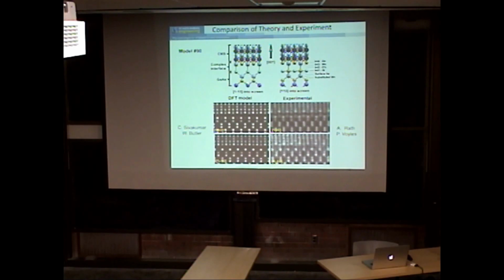Okay, so here now is a model, and you can see here they're trying to simulate this experiment. This is a theoretical image. They're close. I would say they're not perfectly matched. This was model number 90. Okay. Model number 92 might have been slightly better. But basically what it's saying, it's not easy to say this is what you should have. Right? But all we can say is that there are a few layers of exchange of atoms. It appears to be, seems to be in agreement here. Did it require any vacancies? This did not require vacancies, right?